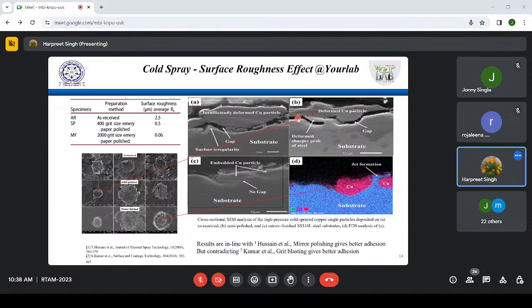Our practice shows that the deposition of the first layer is very, very challenging, right? See, in thermal spray and other processes where mechanical keying is the main mechanism of bonding, there is no contradiction. People say, okay, bring some kind of surface roughness on the surface. It will help us to pin the particles on the surface. But in cold spray, this is not working. We have seen that there are certain combinations where the surface roughness is helping, and there are some combinations where the surface roughness is not helping at all.